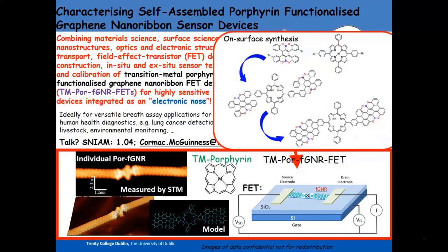One example of what we do is we might take small molecules like this one here, and we could throw lots of these on a surface along with a porphyrin like this, and these can self-assemble into chains. As we heat the surface up, we can establish a polymer chain like this. As we heat it further, we end up with a nanoribbon here, which then incorporates the porphyrin. An example which we have demonstrated is here. This is the actual porphyrin in the middle of our nanoribbon.